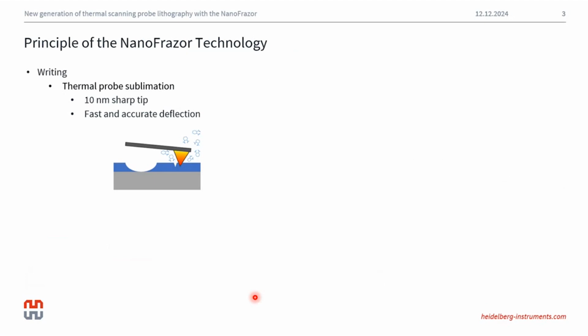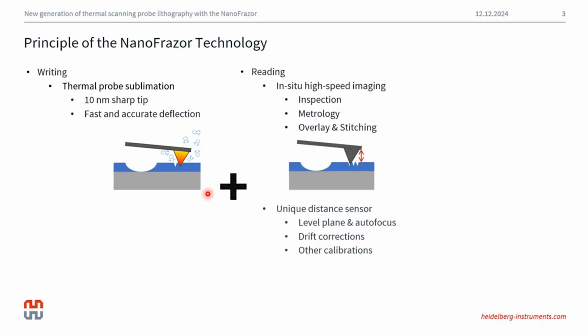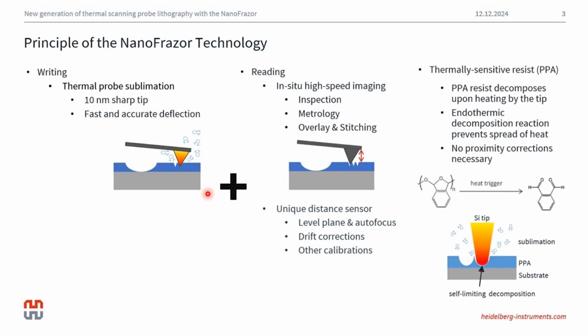So going back to the NanoFrazor technology principle, this is a direct write thermal scanning probe lithography technique that uses an ultra-sharp heatable silicon tip for both the writing and the reading of nanoscale structures. You can think of using the NanoFrazor whenever you need artificially made nanoscale structures on a surface. And here, because we are using heat from the cantilever tip as a trigger for patterning, we need thermally responsive surfaces below. For example, this can be phase change magnetic materials, or in the most standard of cases, we use a thermal resist called PPA. And this resist is commercially available both from Allresist, a company based in Germany, and also from Polymer Solutions based in the US.